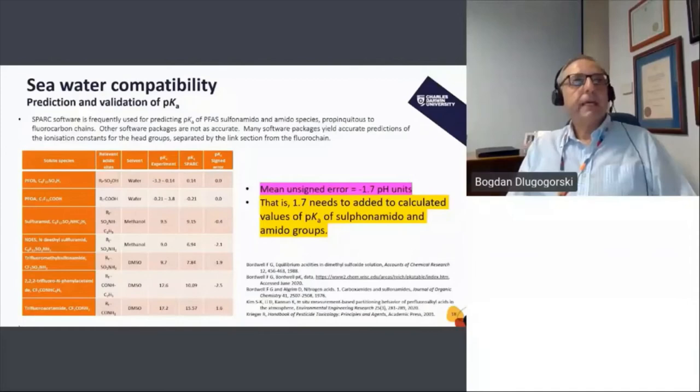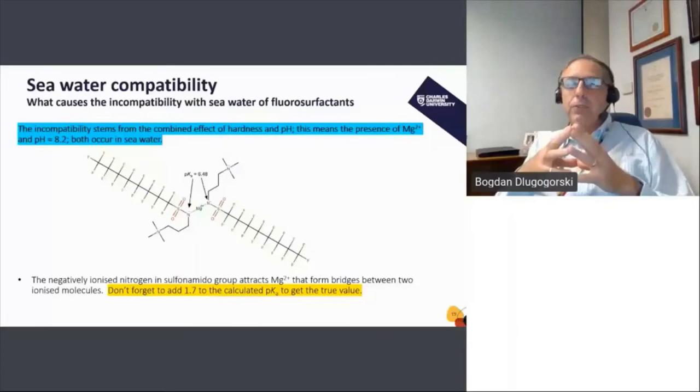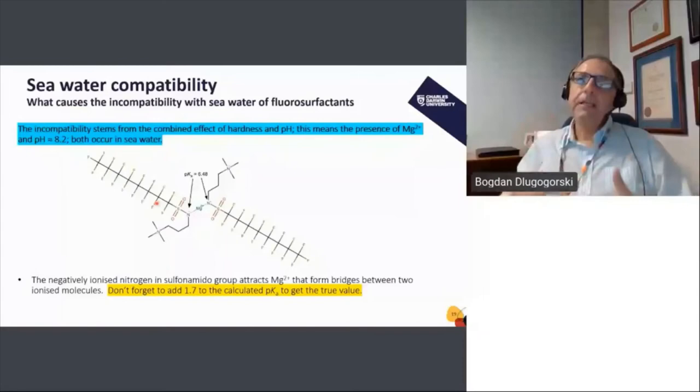And here's probably the most important slide of the presentation because it describes what happens when the foam is not resistant to seawater. Two things must happen. First, the foam must contain hardness, so it must contain magnesium or calcium, and then this hydrogen must deprotonate. When the hydrogen deprotonates, it forms a negatively charged nitrogen, and that negatively charged nitrogen interacts with magnesium ions forming bridges, and suddenly the molecule is twice as long, and the molecules precipitate. You can observe haziness in the formulation,